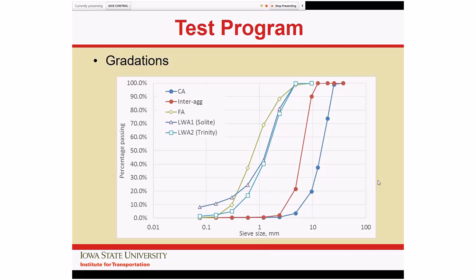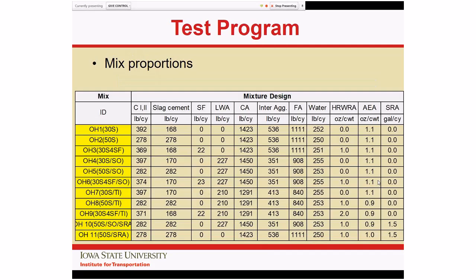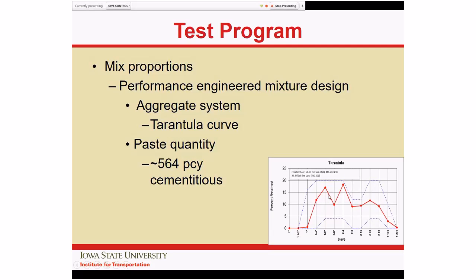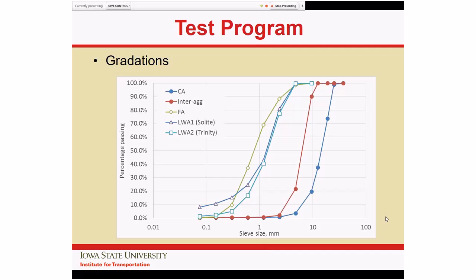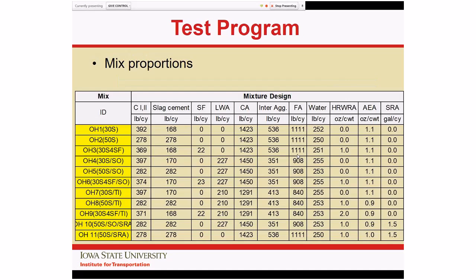Here are the plots of the gradations. It's not a lot of information in this chart. But the real interesting one is this tarantula curve at the bottom, in that we ended up with a pretty good gradation at the end of the day. What is interesting is that both the lightweight fine materials are these two. They're a little bit coarser than the fine aggregate, but they help to straddle the gap between the coarse and the fine material. So they actually provide us with a slightly better gradation at the end of the day.